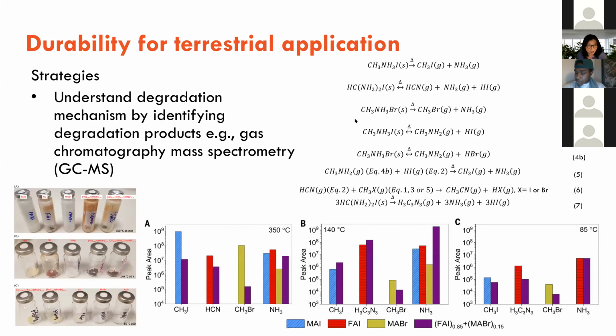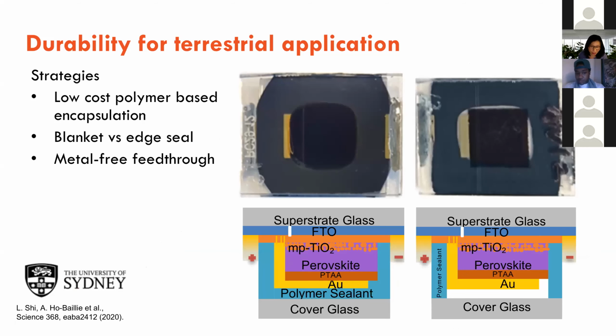Anyway, what we did was we tortured the perovskite materials at high temperature to make them outgas, and then we identified the products. The GC separates the mixture into different components, and the MS, depending on the mass of the compound, lets us identify what they are. So you have all these signature products, and then you can find out what the thermal decompositions are like. Then you use the signature products to evaluate the effectiveness of your encapsulation.